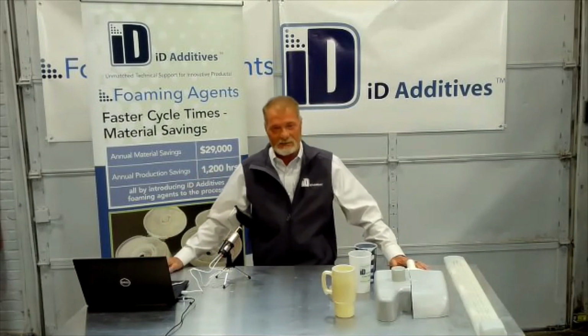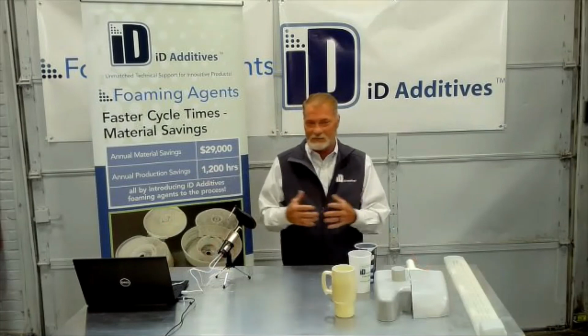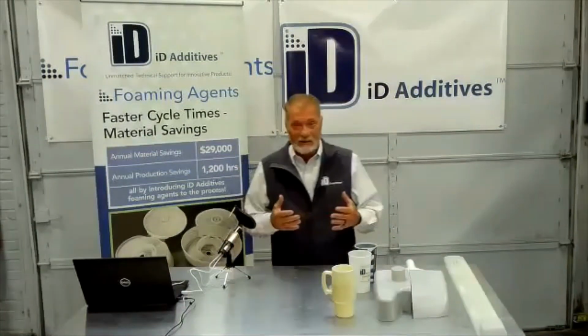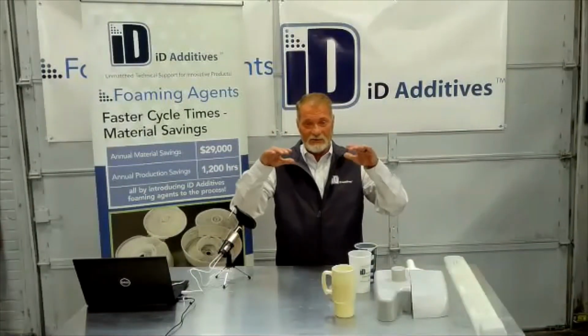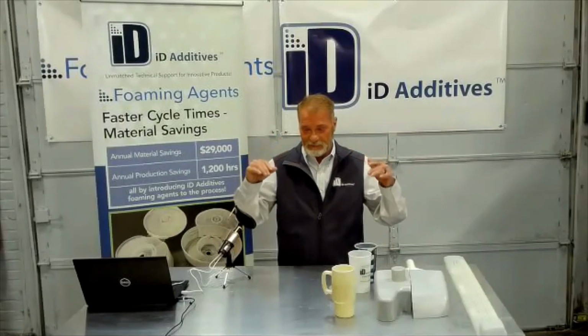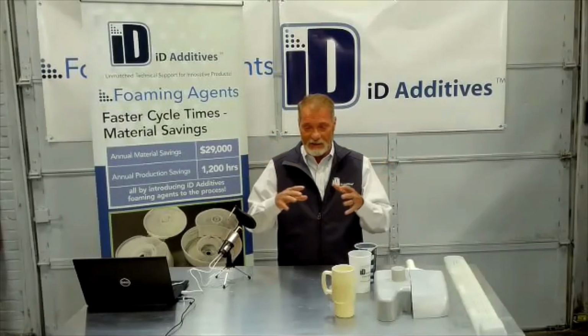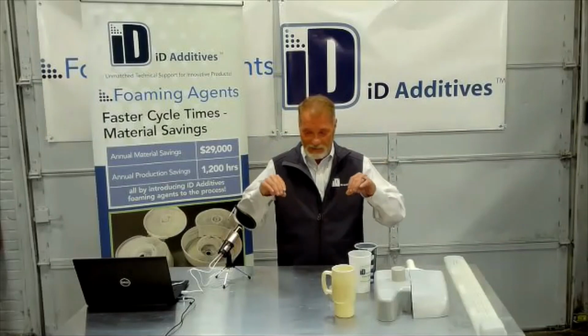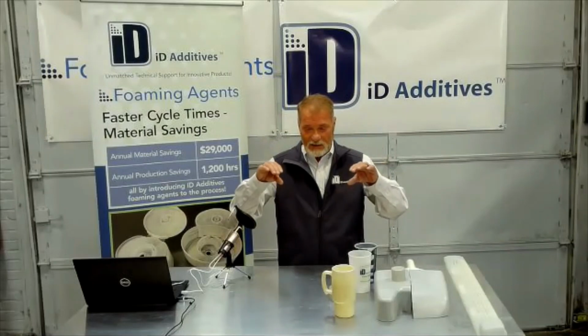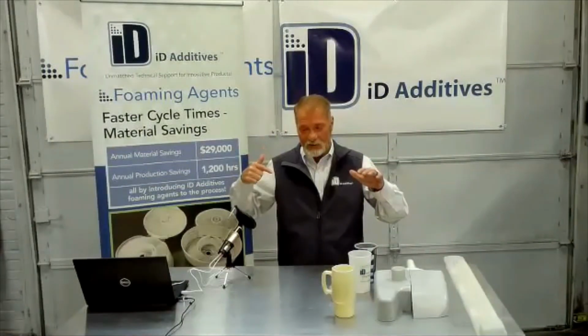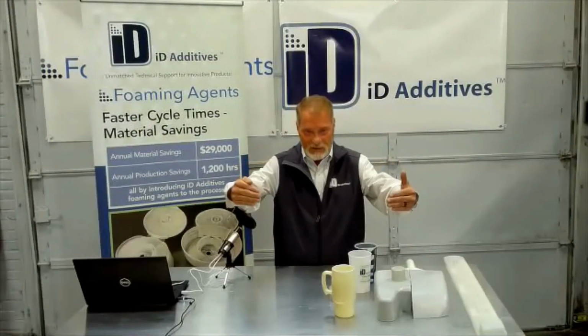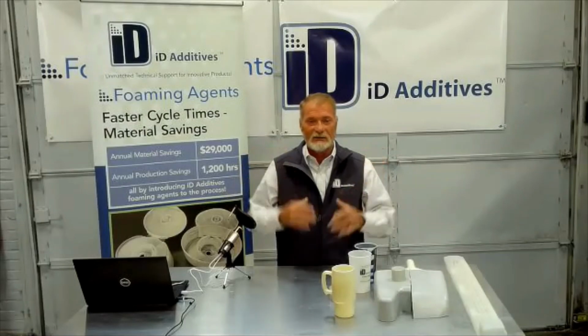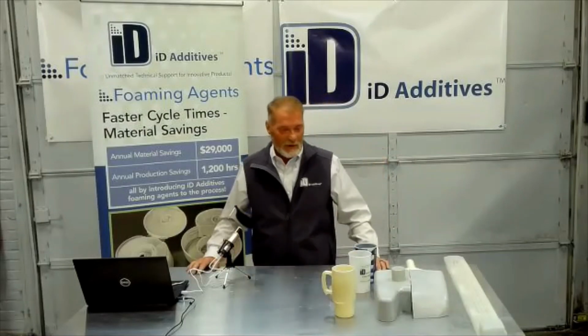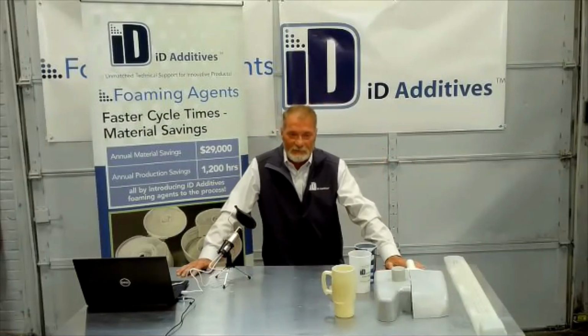Because once it exits the die, it wants to expand a little bit because it's ambient air. So then it goes into calibration, and when even a sheet, it'll swell up. So you can either adjust the die lip, you can turn the RPM down, or you can just speed the line up a little bit, pull it down to gauge, and take advantage of both the weight and the speed.